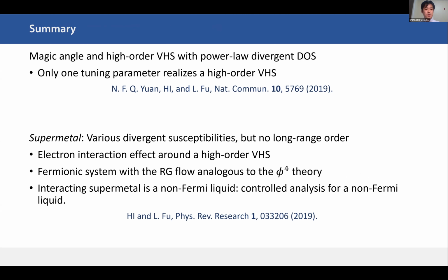Okay, so let me summarize my talk. In the first part of my talk, we introduced the high order Van Hove singularity from a continuum model of twisted bilayer graphene. And we redefine the magic angle as the critical twist angle where we see a power law divergent density of states instead of a log divergence at a saddle point in two-dimensional electronic dispersions. And we need to tune only one parameter, for example, twist angle or uniaxial strain or pressure, to realize high order Van Hove singularity.